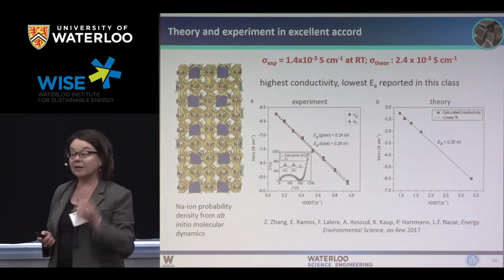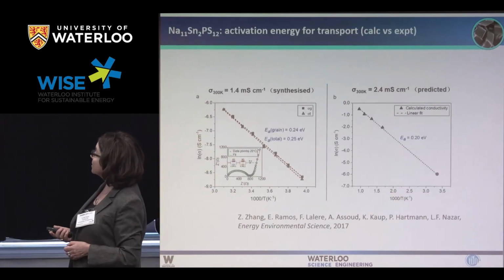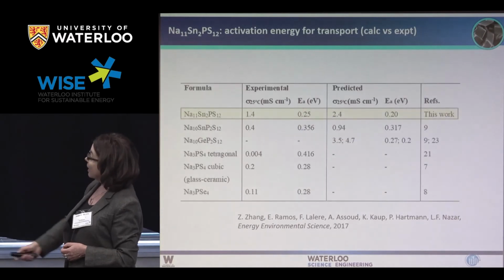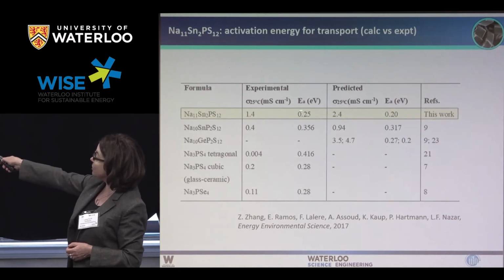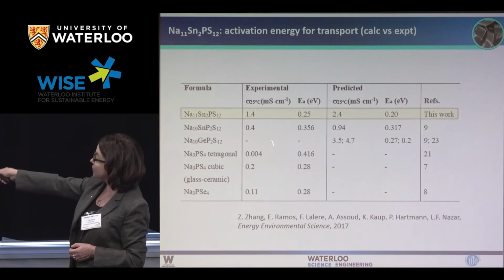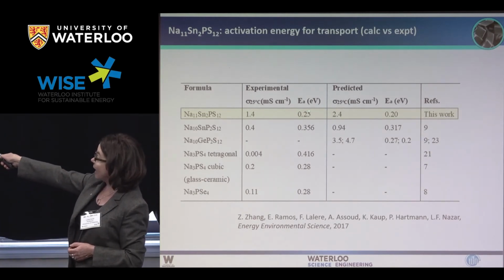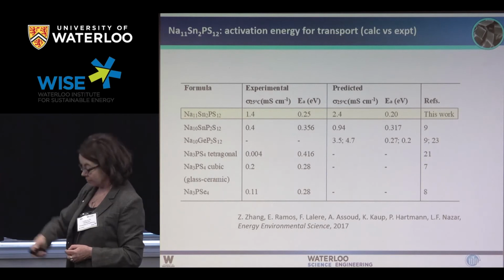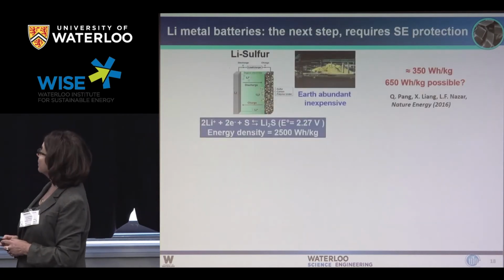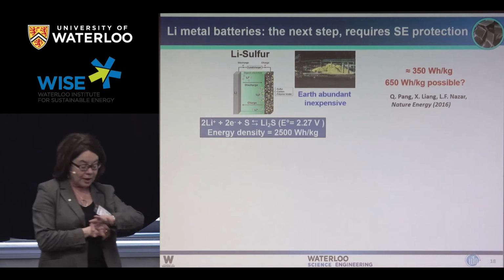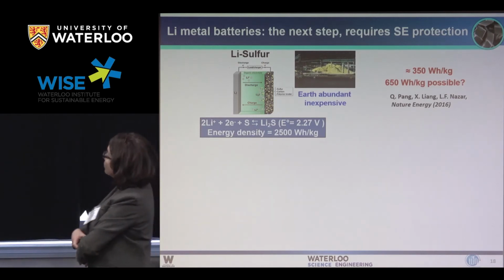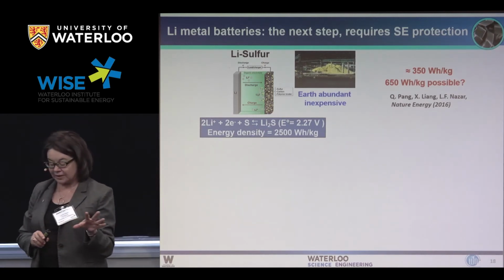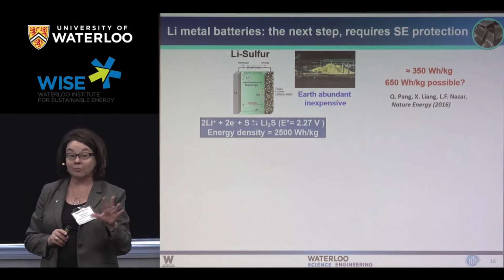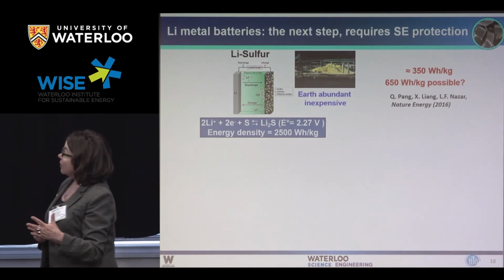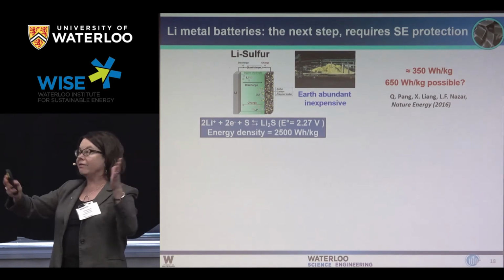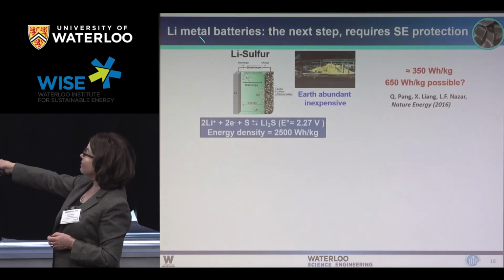So we are currently trying to make this into some solid-state sodium-ion batteries in my lab. And this just shows a comparison of the values that we have to those others in the literature. And you can see that the conductivity is significantly higher and the activation energy is significantly lower. So, as I said, I don't want to bore you with too much chemistry. So I hope I've convinced you at least that solid-state batteries are certainly a way forward, both for lithium and sodium. The other big thing these days is lithium metal batteries.